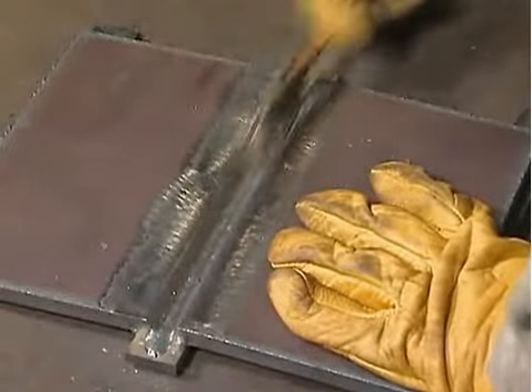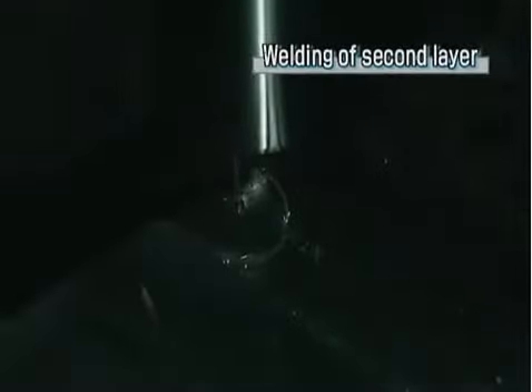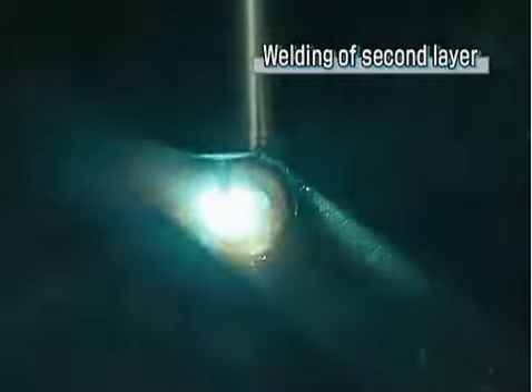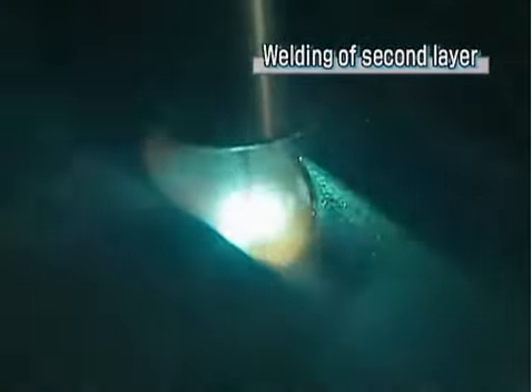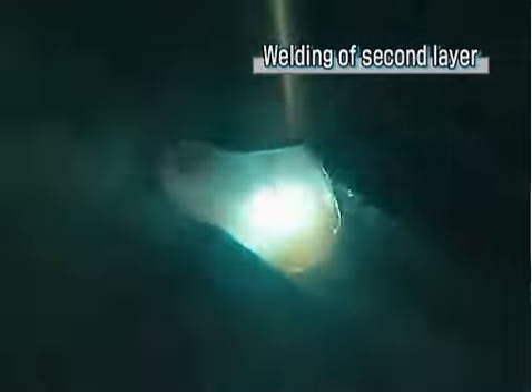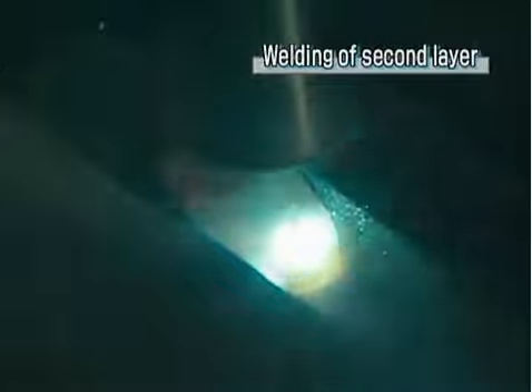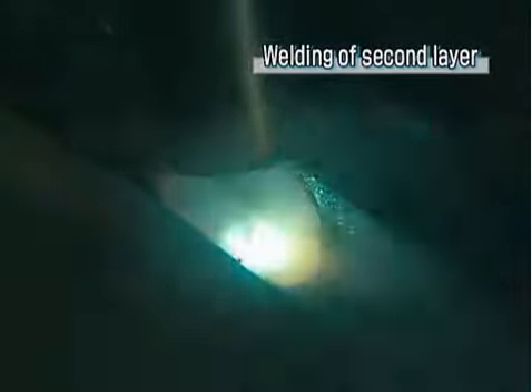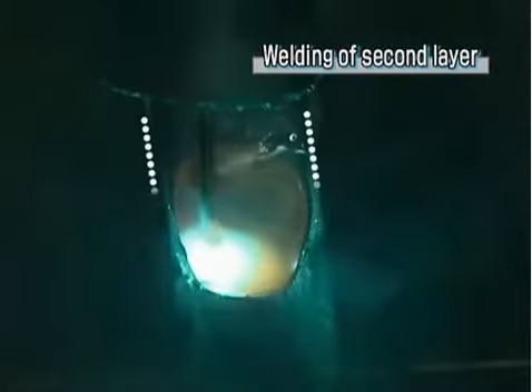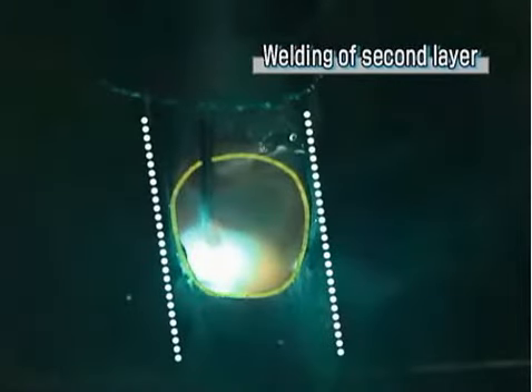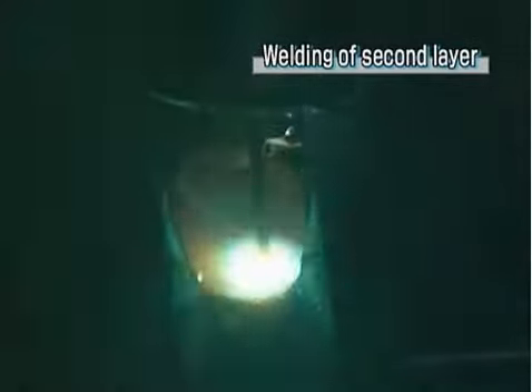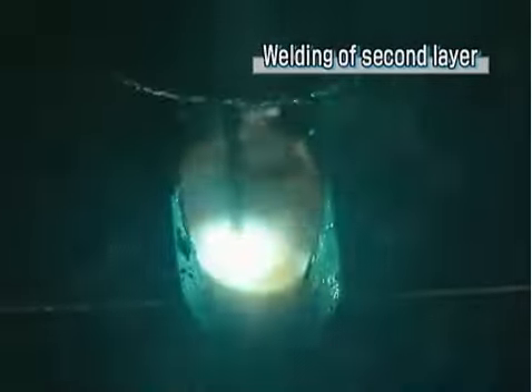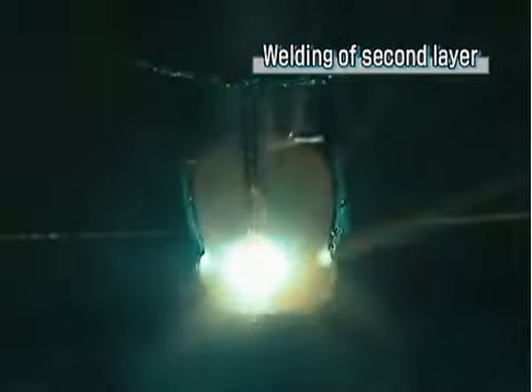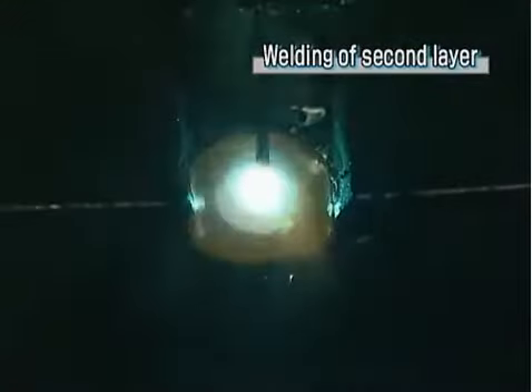Thoroughly remove the slag or spatter from the first layer. For the second layer, use the forward push method and weave from the end of the first layer bead. When weaving the torch, pause briefly at both sides to allow sufficient penetration between the first layer bead and the groove face. One other point to be aware of when welding the second bead layer is to keep the outside line of the weld pool 1 to 2 millimeters below the groove face. This will create a clean finishing layer.